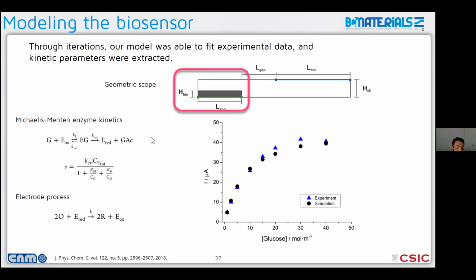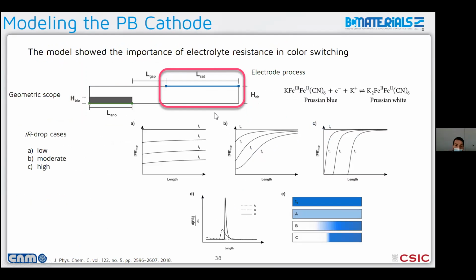So first we checked the biosensor model. We used the model to extract some parameters from the experimental value, and we saw that, okay, we have something that resembles the experiment. Did the same with the Prussian blue electrode. And here, what I'm showing you in this slide is the importance actually of the IR drop. So in these three cases, what I'm showing is low IR drop or a moderate IR drop. This is cell resistance. And the way we modeled this was by increasing the volume of solution over the surface of the electrode.